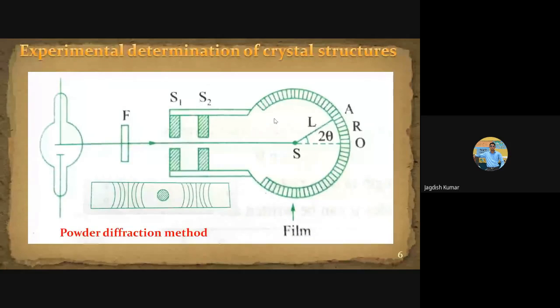So these two circles, the circular arrangement of the photographic plate and the circle perpendicular to it, have exactly the same center. That is why these peaks are going to be straight. I am bringing your attention to these peaks because they act like a reference. Those straight lines refer to the 90-degree situation. That is how we can employ even powdered samples for measuring the X-ray diffraction pattern of any crystalline material.